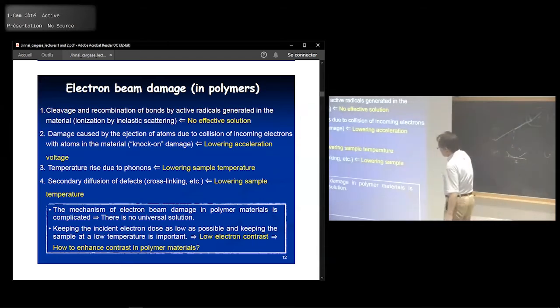This is always a discussion, I would say. Some people say lowering the acceleration voltage is good, better than the high voltage. But some people say, no, the higher voltage is better, because higher voltage electrons have a lot larger energy, and they transmit without interacting with the sample. So it does not damage the sample. There's a discussion like that. So it depends. Actually, the answer depends on the sample, and it's true for biological samples too.